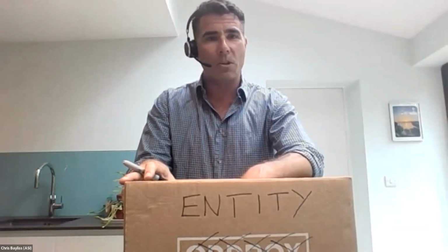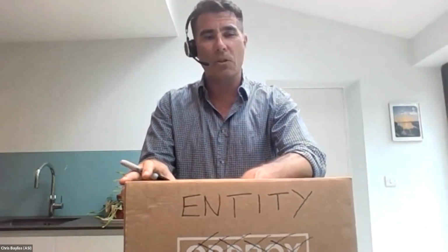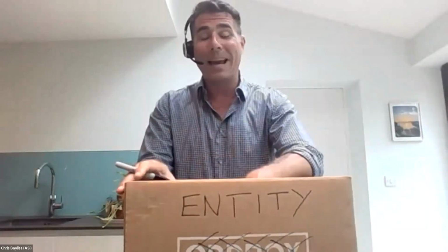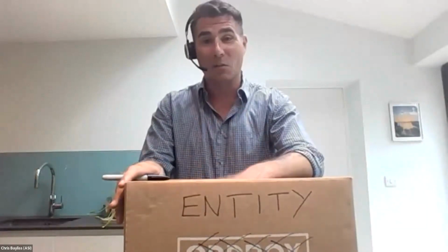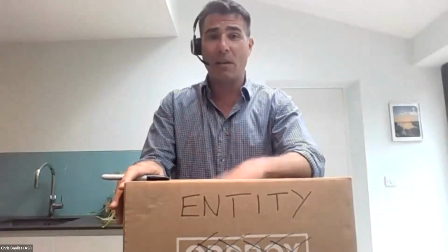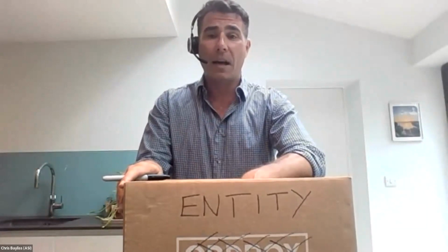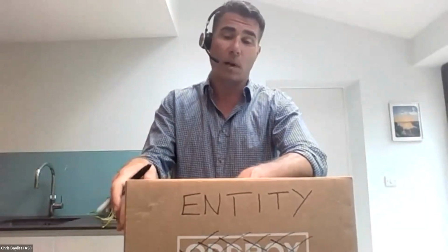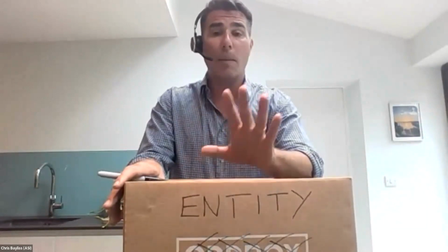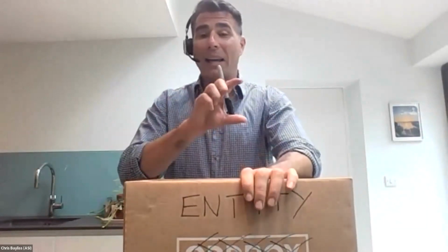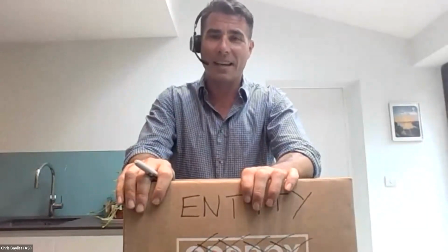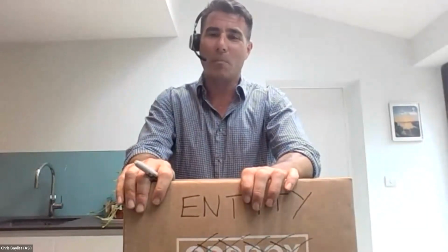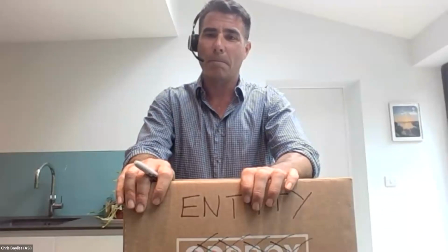One final question has come in. What is the CO2 footprint of pre-consumer and post-consumer scrap? It can be anything from 0 to 20, right? Post-consumer scrap is generally recognized to have an allocation of 0 emissions. So the post-consumer scrap you treat as 0. Pre-consumer scrap, that's the big question. Do you allocate 0 or do you allocate the same as the product? And I would say today, both of those approaches are valid.